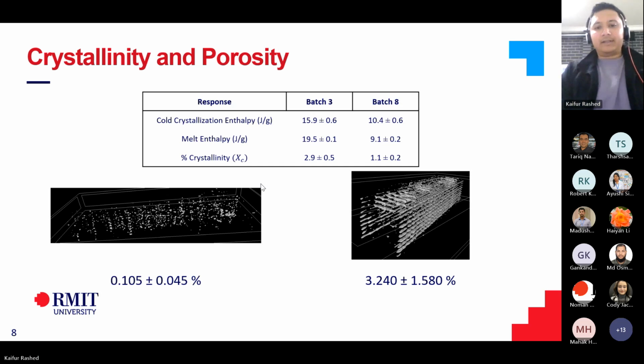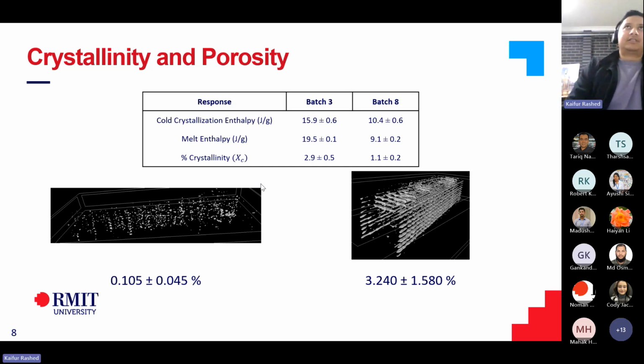And the reason why that happens is that since I used a printer which is custom built, it did not have a heated chamber. So I only had a heated bed. As the flat samples were quite thin, they were close to the bed, so they were mostly heated the whole time. But the samples that were on edge were quite tall, so as the nozzle went far from the bed, it did not have as much heat, so a thermal gradient developed, and that's what caused so many pores. And that can also cause reduced interlayer lamination as well.